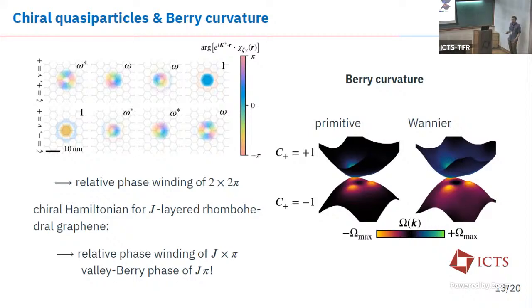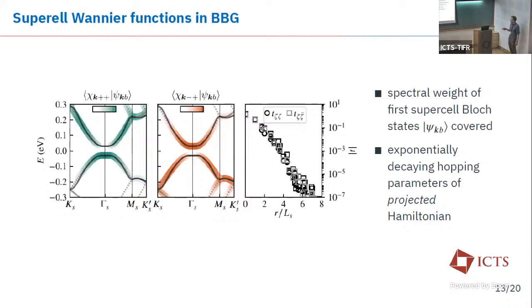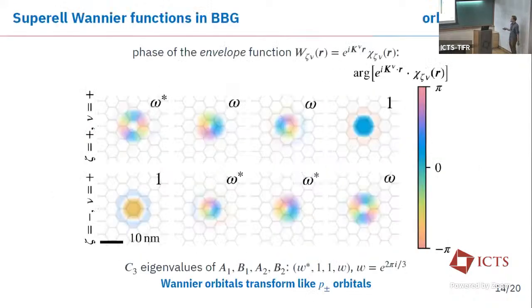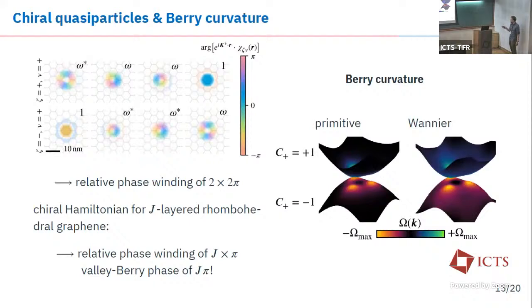Although at higher energies, you have some mismatch, and this is for the same reason that you have mismatch here in the band structure. So the thick black lines are the Wannierized model, and the dotted gray lines are the supercell model. And you see that at the Brillouin zone edges, you get a mismatch because you write down a 2-orbital model to reproduce the band structure of a connected set of bands. And this is also the reason for the Berry curvature being kind of different at the edges of the Brillouin zone. But at the center of the Brillouin zone, we perfectly reproduce what is actually there in the primitive cell model.